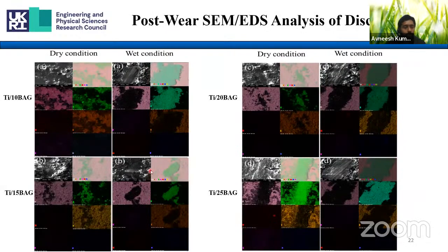Then we tried to see whether there was some transfer of material from the coating surface to the counter surface, and for that we did SEM and EDS analysis of the counter surface, that was alumina. For alumina, we found that in every case there was some titanium, which is green in color. This means that material has transferred from the coating surface to the counter surface. The reason can be that when one surface is rubbing the other, there will be a high temperature rise at the contact, and that will cause the development of weld junctions between the coating and the counter surface. This will lead to the transfer of material from the softer coating surface to the counter surface, that is the alumina surface.